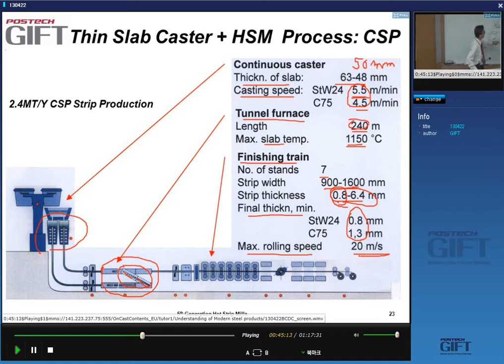Rolling speeds are of course not as low as this example I suggested. So don't forget this number if you've written it down. This is an imaginary number, yes, that you would end up with if you would feed this casting speed directly in the finisher mill, yes? Obviously, that's not being done. You have these parallel tunnel furnaces, and so you can move up to 20 meters per second.